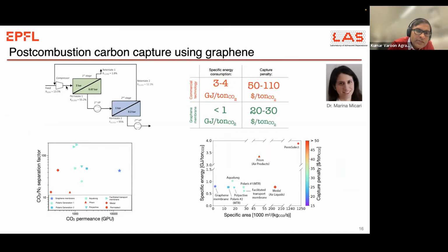It can be compressed to a higher pressure, so 2 bar. And on the other side of the membrane, which we call the permeate side, we can use a vacuum pump to pull a moderate vacuum. With this we can already go from 13.5% to about 50%. So we have gone half the way in purifying this. Then we can do a second stage where we don't have to pressurize anymore, but on the permeate side we pull a weak vacuum, about 0.2 bar, and then we can recycle. In this way, we can get up to 95% purity of CO2.